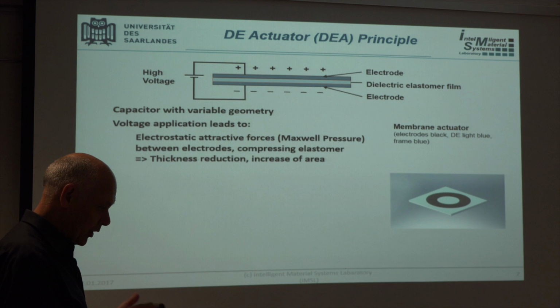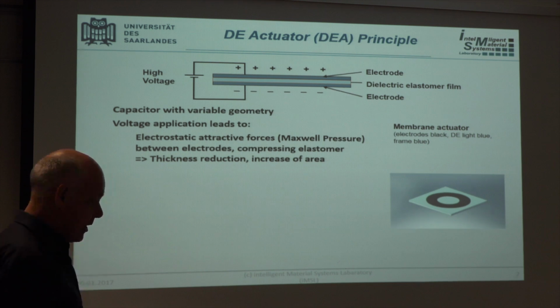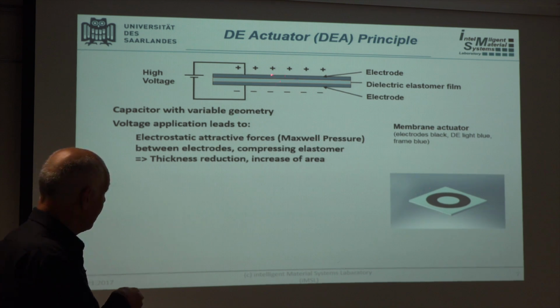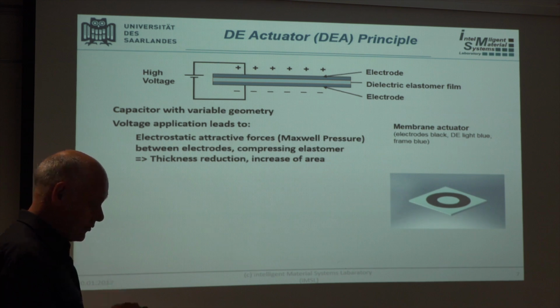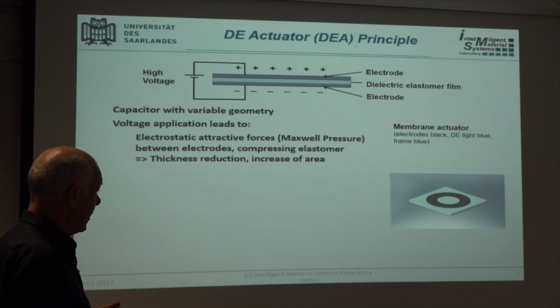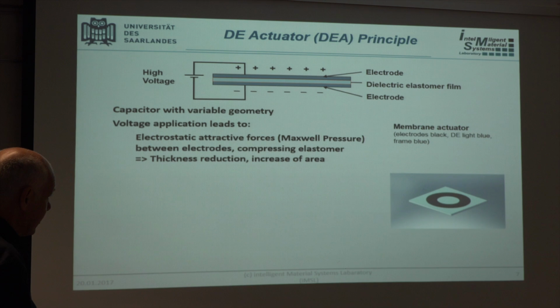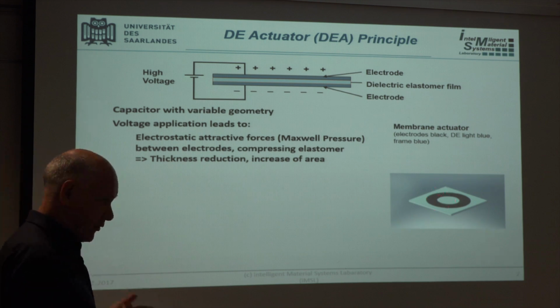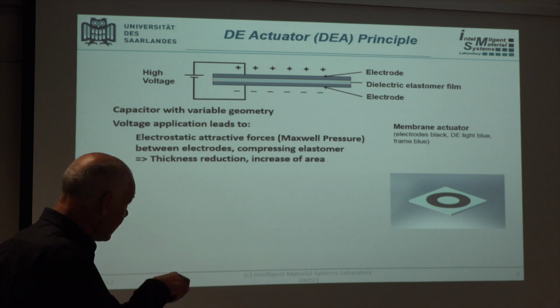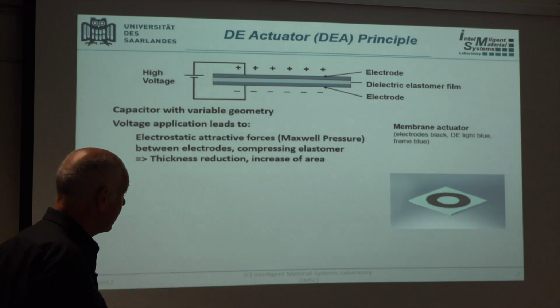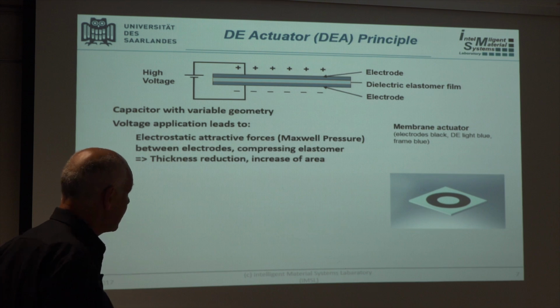So the electrodes bond nicely on the silicone, but they can also deform over a very large stretch range, which is very important, because if you want actuation from it, you basically have two competing effects of providing good electrical conductivity while also providing a large mechanical deformation, which typically doesn't go very well together. But this mix guarantees that we can find a good compromise, and so this is why the electrodes are a fairly important contribution to a dielectric elastomer.